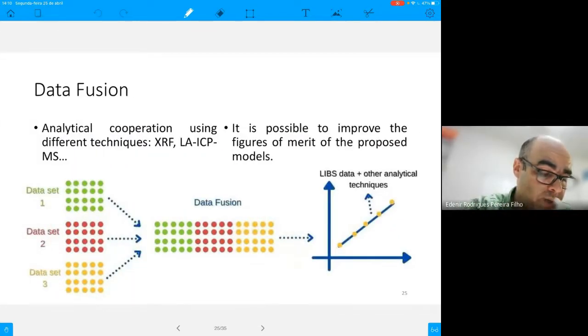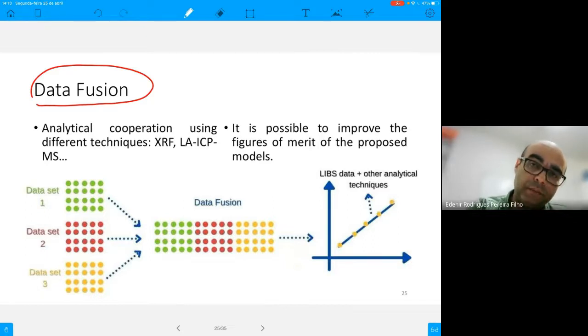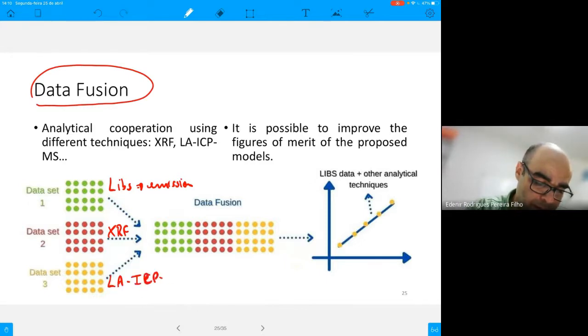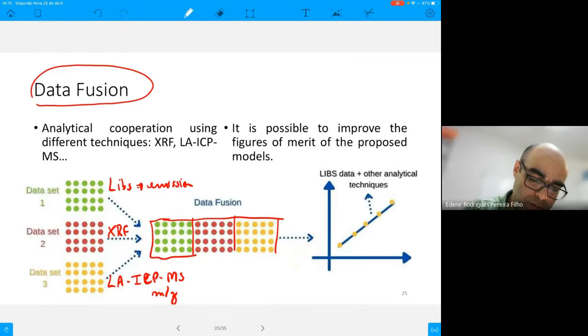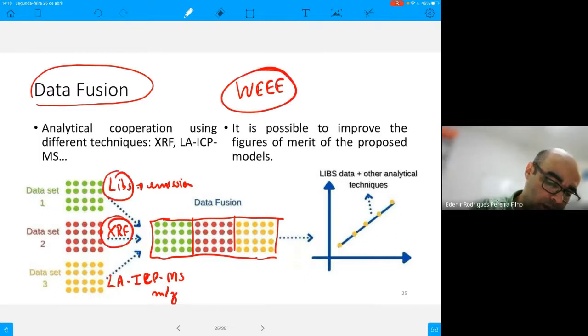Data fusion. Data fusion is a very good strategy. We can combine, for example, different techniques with different natures. For instance, we can combine LIBS, an emission technique, with X-ray fluorescence, and also laser ablation ICP-MS, where you have the mass ratio as data. We can make a fusion of this data in order to obtain a calibration model with better figures of merit. We performed this for electronic waste analysis, combining LIBS, X-ray, and also laser ablation.